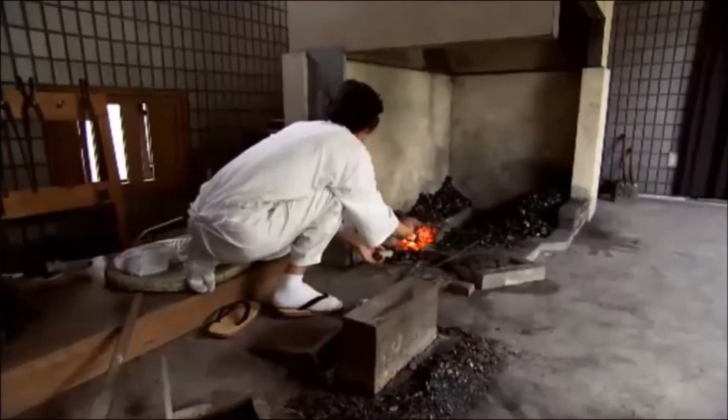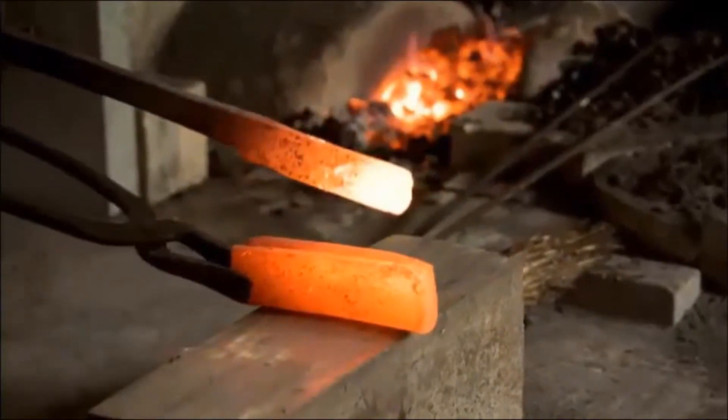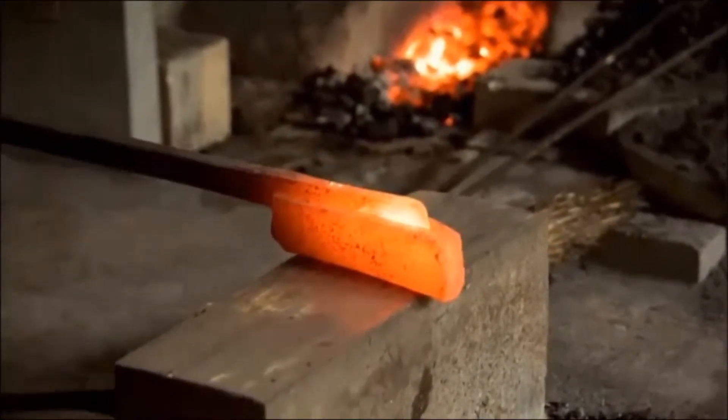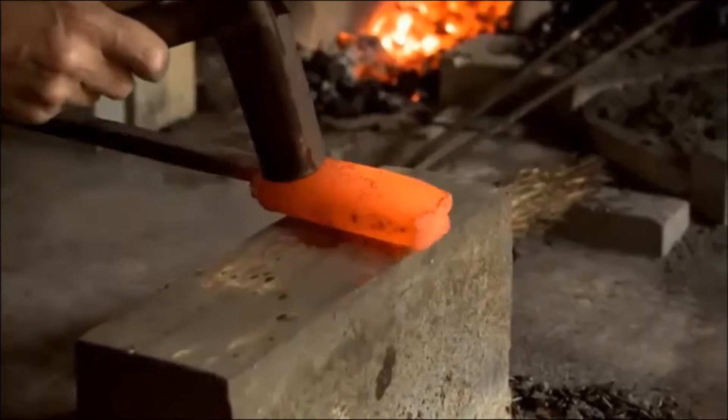Now is the crucial moment when both types of steel are forged together. The hard steel is pounded flat and then folded into a U-shape. The tougher, low carbon steel is heated to a glowing red and inserted into the core. The hard steel is wrapped around the outside to allow for the cutting edge to be razor sharp. And at the core, where the sword needs to absorb the impact of those deadly blows and be more flexible, Gassan uses the tougher steel.